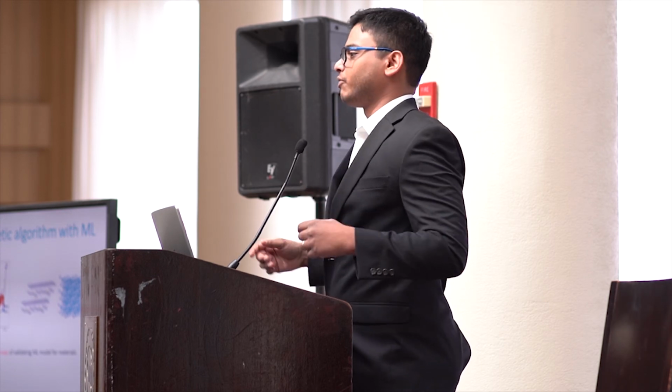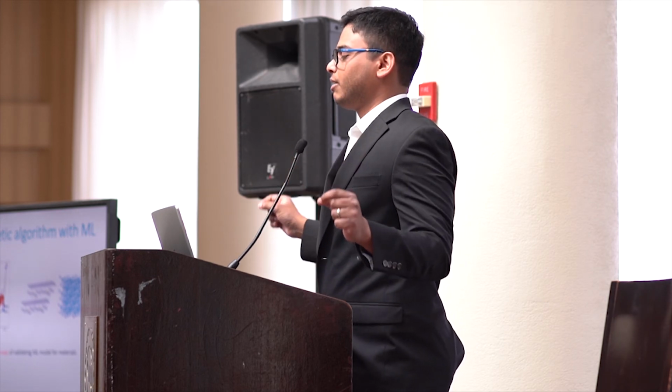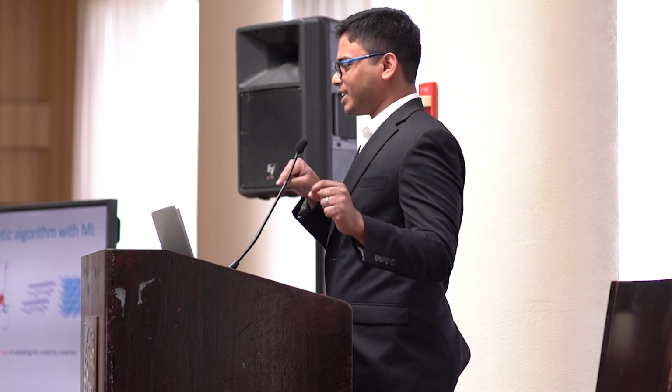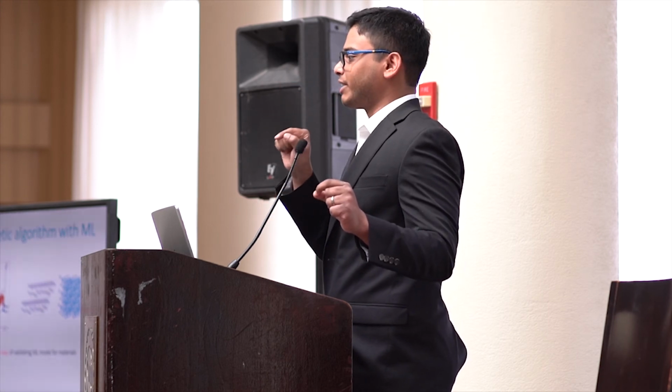For Mo and S, we made 5,000 children structures. And guess what? Only about 8 or 9 survive. You see the blue dots? These are the surviving children, and the others, the red dots, die away. We found, interestingly, that MoS2, which is known to be a stable structure, is actually stable even in machine learning. I just don't know how to explain how big an achievement it is, but it really bridges the gap between the machine learning and the materials science community.